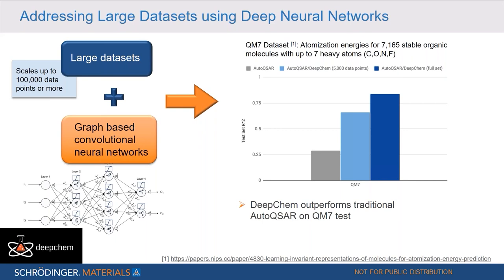the Schrödinger suite also offers automated deep learning approaches, namely AutoQSAR DeepChem. This approach uses the DeepChem open source package and is based on graph-based convolutional neural networks. What we see here on the right-hand side is a plot which depicts the R-square values for the atomization energies for over 7,000 stable organic molecules. We can see a comparison between AutoQSAR and AutoQSAR DeepChem for a smaller data set and the full data set. And we see that the R-square value is rather low for traditional AutoQSAR, it's in gray. But we can see that it increases already significantly for AutoQSAR DeepChem if we take a set of 5,000 molecules, and even more if we go to the full data set, which is shown in dark blue.